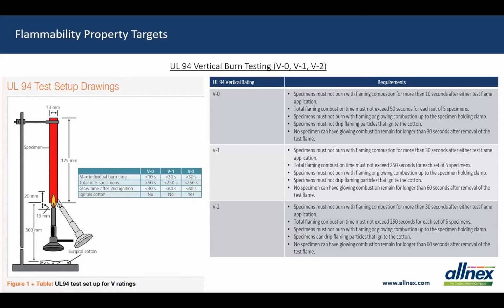And if we have a look at the UL94 test, the standard itself, this is an overview of what the test is about. We can set a target of V0. The UL94 basically specifies tests where the test specimen, it could be a laminate or a cast strip, is supported in a vertical position in a clamp, and flames are applied to the bottom of the specimen. So the flame is applied for 10 seconds, then removed until the flaming stops, at which time the flame is reapplied for another 10 seconds and then removed. V0 in this table is the most difficult to achieve, and the most significant part of all of that is that you can't have any continued combustion. It's got to self-extinguish within 10 seconds after each flame application. Not always as easy as it might seem for a lot of materials, but it's a good screening test which we're applying in this case as well.